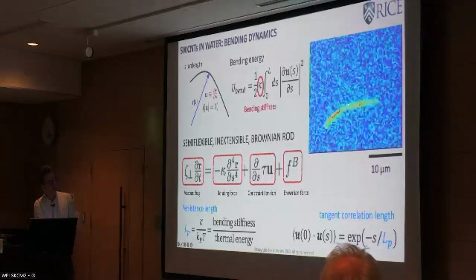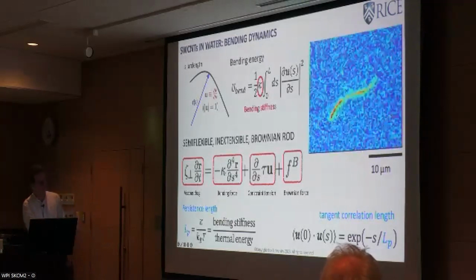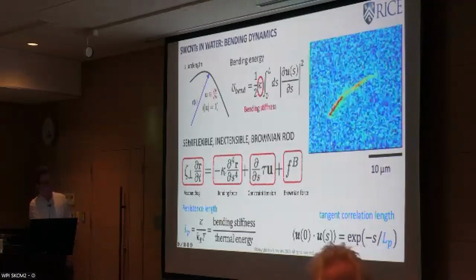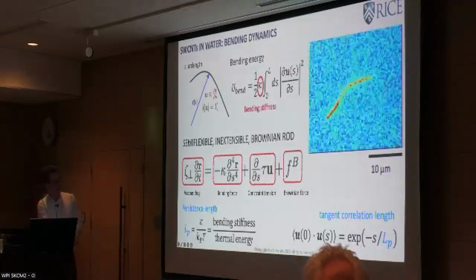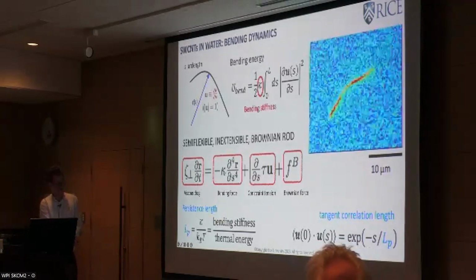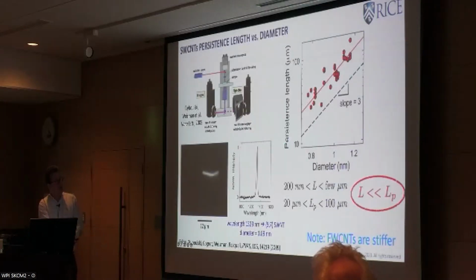Now, if you go to higher concentration, to longer nanotubes, what you see is that they actually start fluctuating in shape like semiflexible chains would do. And you can actually back out the persistence length by looking at the correlation length of a tangent. And you can then measure it. And you can also measure the diameter of each nanotube, not microscopically, but spectroscopically, by taking the photoluminescence spectrum of each tube, which is uniquely correlated to the diameter. And you see that the stiffness of these molecules goes with the cube of the diameter, as you would expect for an empty shell.